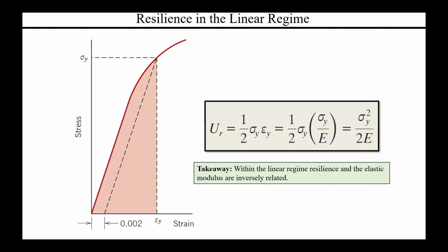So since we're in the linear region, we have a pretty nice little heuristic relationship between the elastic modulus and the resilience. This is particularly useful if, for example, you have the yield strength and the elastic modulus. It gives you a nice, easy way to estimate what the resilience would be without having to have an actual resilience test or this continuous stress strain relationship. You may only need really 2 or maybe even 3 points: your yield strength, your origin, and a point along the elastic region to get your elastic modulus.